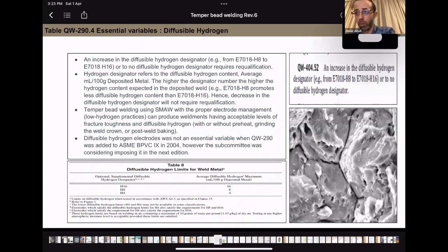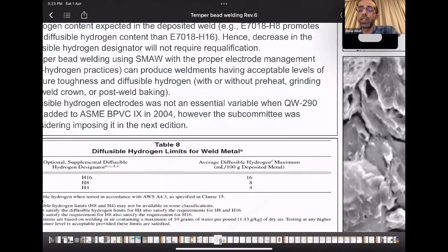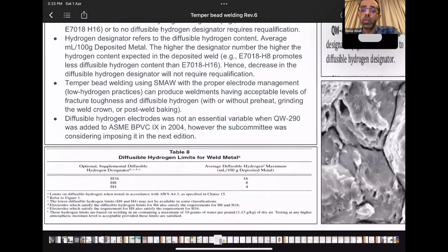So the increase in diffusible hydrogen will require a requalification. Why increase? And what do we mean by diffusible hydrogen? We have a hydrogen designator in the electrode specification or number. And these numbers are given in Table 8 of ASME Section II Part C. And as we can see here, H16 is the average diffusible hydrogen expected in the deposited weld in milliliters per 100 grams of deposited weld. This is 16. So the higher the value, the higher the expected hydrogen content in the deposited weld.